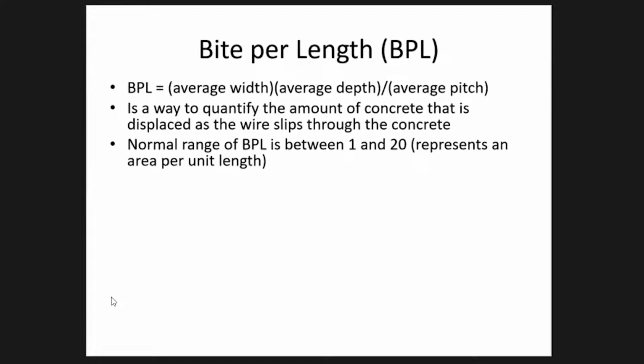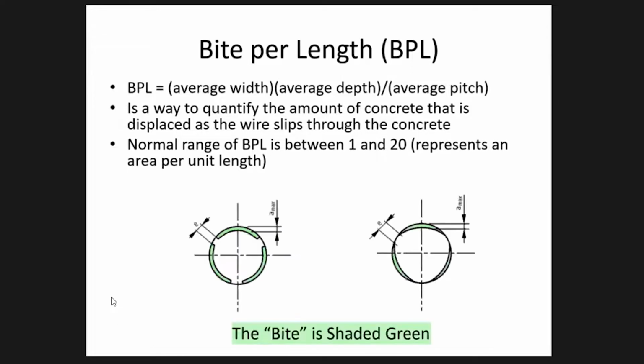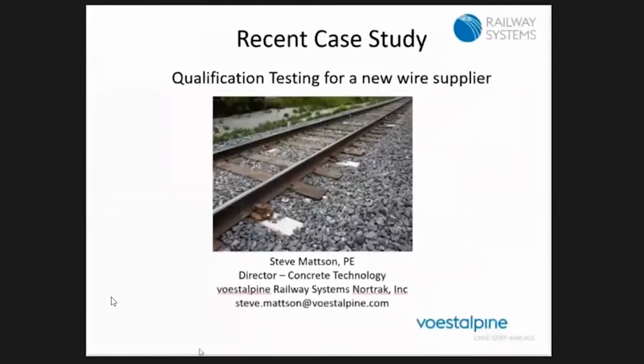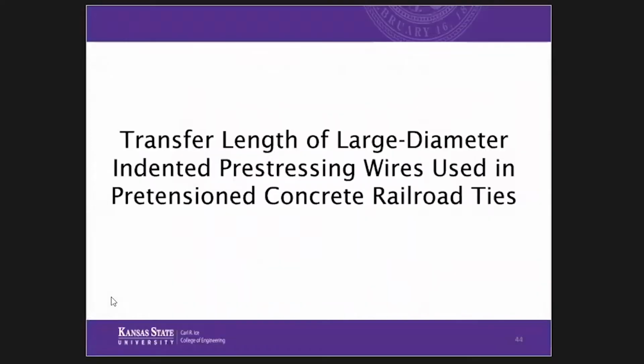Otherwise, we're dealing with numbers that are like 10 to the minus third powers, or up in the tens of thousands, if you use millimeters squared per inch. But it's a relative measurement of width times depth over pitch. In these same two pictures, the T2 on the left and the T4 on the right, the green area would be the bite, and then we divide that by the pitch in and out of the page. Steve Mattson at Nortrak and I gave a talk at this conference last year, which was virtual. If you want to hear from a producer's standpoint, Nortrak used the concept of bite per length, and it was very helpful as they looked for a new wire supplier and quantified a wire. I would plug that if you want some more information.